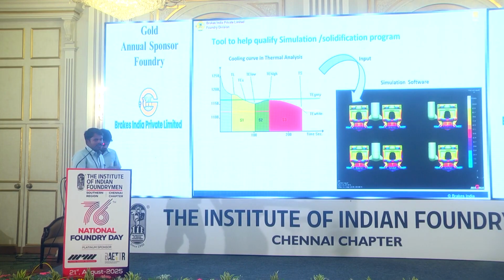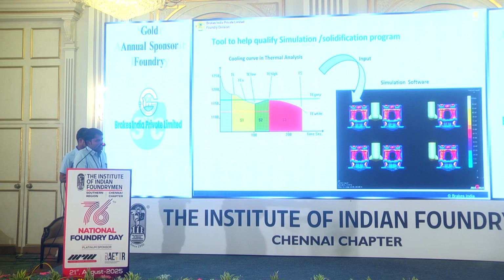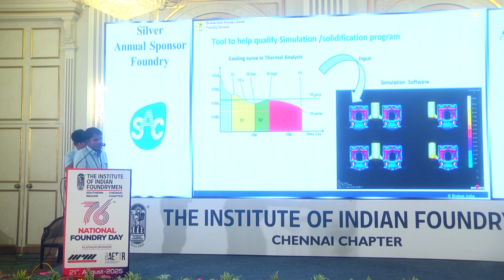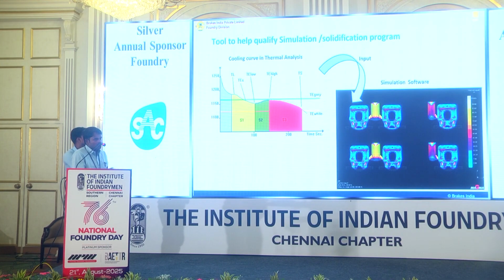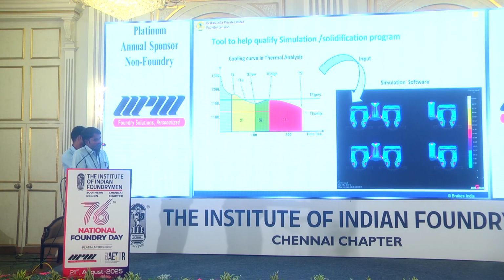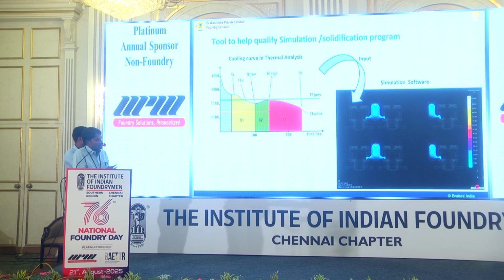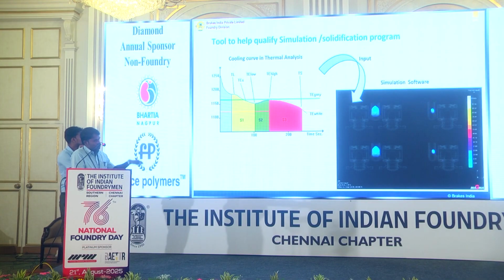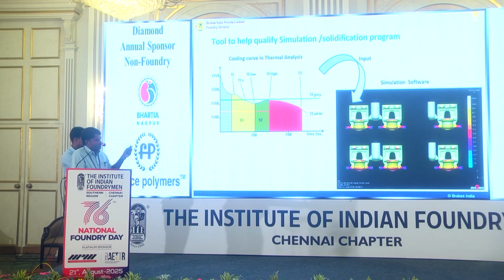With thermal analysis, we can also use this time temperature curve in the simulation software by injecting it into the simulation software. So we can proactively eliminate the shrinkage, and we can assure more precise simulation by injecting this real-time time temperature curve into the simulation software, in addition to the chemical composition and other parameters.